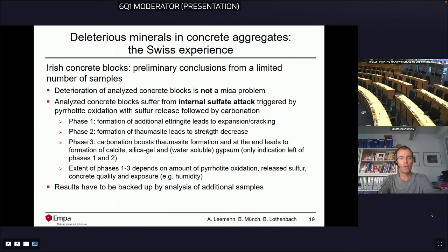The extent of phases 1 to 3 depends on the amount of pyrrhotite oxidation, and with that, of course, the amount of released sulfur, concrete quality, and exposure, which means humidity. Humidity accelerates the reaction. And the results should be backed up by further analysis of concrete samples. Next and last slide, please.